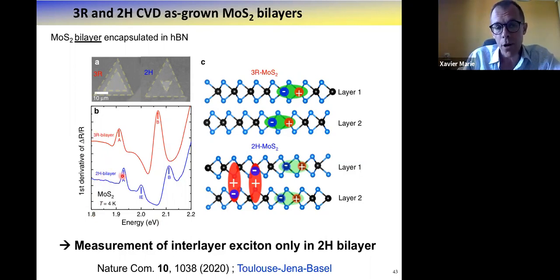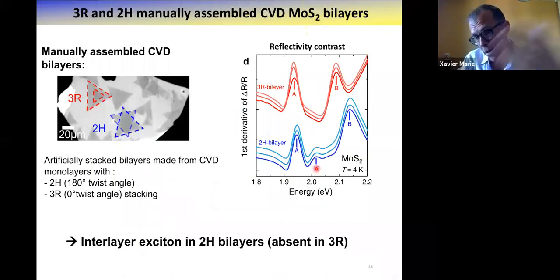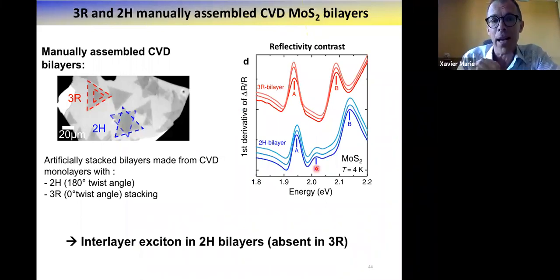In the 2H bilayer, again, as I already showed you, the interlayer exciton is there. But for 3R, it's clearly, obviously not present. So in 3R, what you have is only intralayer, whereas in 2H, you have both the interlayer and the intralayer. And in fact, we checked this with another way to fabricate the bilayer.